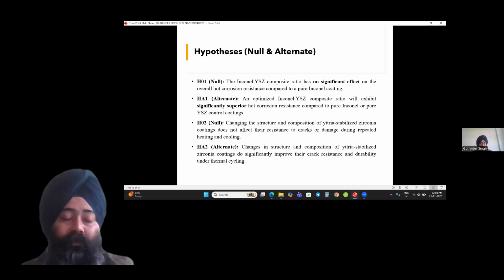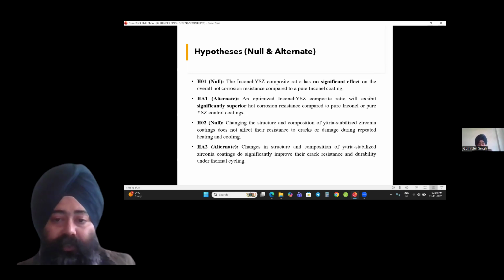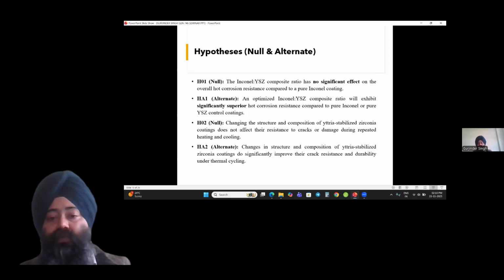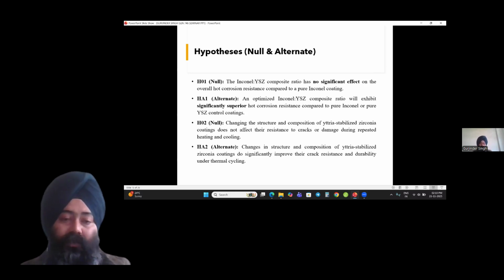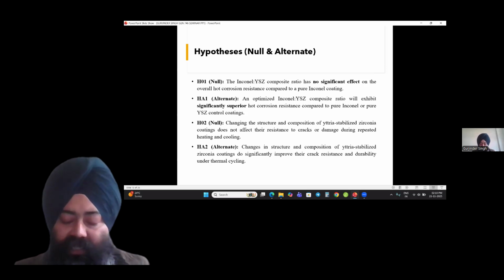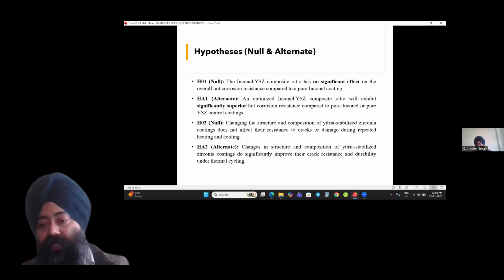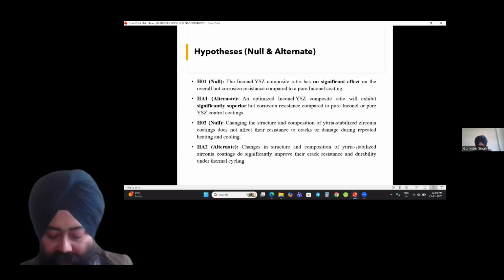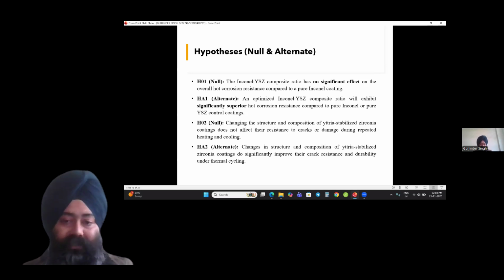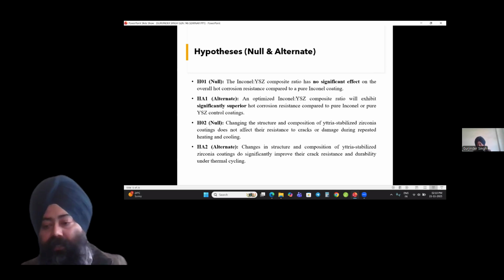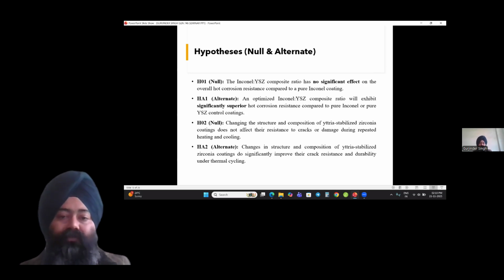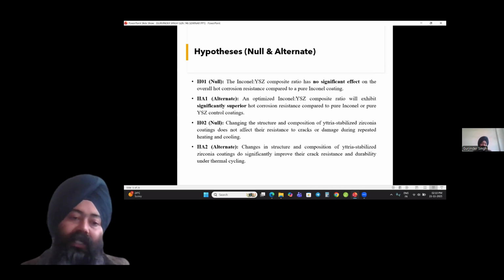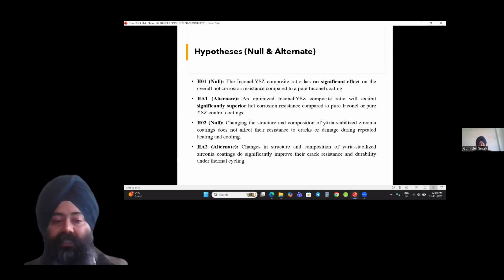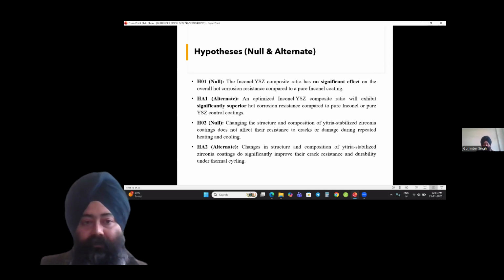And what are the other null hypotheses? Changing the structure and composition of YSZ coatings does not affect the resistance to crack or damage during repeated heating and cooling. As I discussed earlier, there is a limitation of YSZ: when used alone, the YSZ material may result in cracks due to mechanical stress. The null hypothesis is that using a YSZ and Inconel composite gives no improved resistance to cracks. The alternate is a significant improvement in crack resistance with the use of the composite.